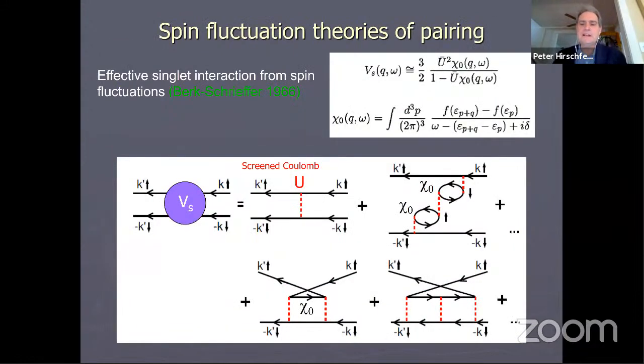Okay, so let me go into a little tiny bit more detail of these theories of spin fluctuation pairing to see a little bit of the guts of the machinery here. The idea here is that if you do essentially what Kohn and Luttinger did, but go a little bit further and sum a subclass of diagrams, then you can find that the interaction V of Q and omega up here is essentially proportional to the magnetic susceptibility of the system, the dynamical susceptibility, in the random phase approximation. So in the random phase approximation, this is a picture of superconductivity that comes from the exchange of so-called paramagnons rather than the exchange of phonons.